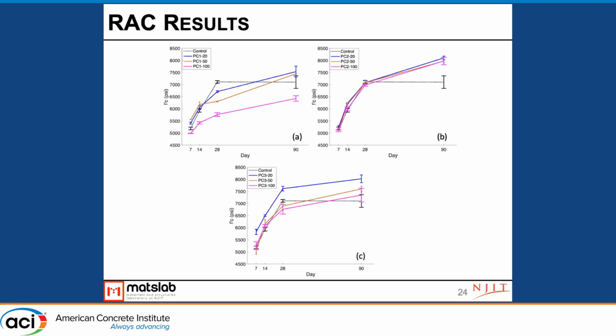So these are the compressive strength results of basically every mix we did in the study. What you're looking at is, in A, we have the first parent concrete strength group, and then on the top right, B, we have parent concrete 2, and then on the bottom, we have the third parent concrete. Again, remember that the parent concretes are increasing in strength as you go from 1 to 3. What we're seeing here is that the first group definitely did not perform as well.